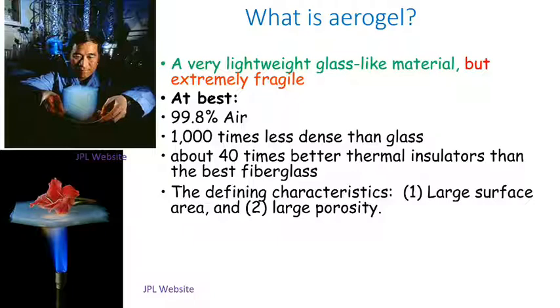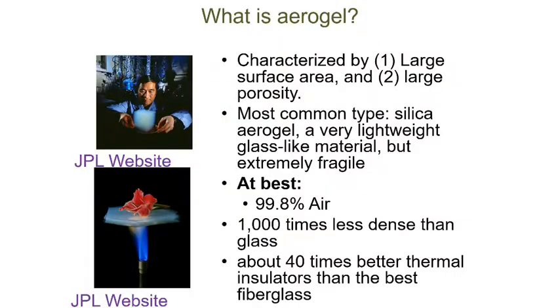So with aerogel, what we are doing is simply making them as porous as possible. We are removing as much of that density as possible. But the main, or the defining characteristic, is that they have a very high surface area, extremely high surface area. You can see something like 3,000 square meters per gram when you use this. So that is a big number, right? Also, they have a very high porosity, as you can see, like 99.8%. So these are the main defining characteristics.